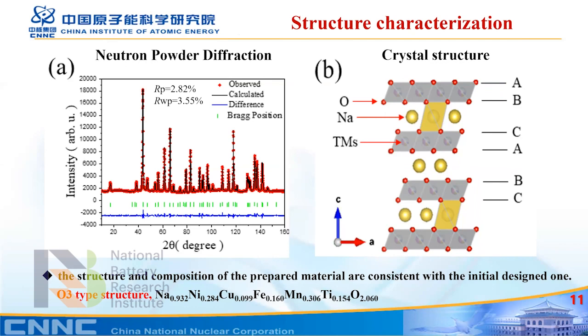That is sodium 0.932, nickel 0.284, copper 0.099, iron 0.160, manganese 0.306, titanium 0.154, oxygen 2.060. The design, I think, is a very good matching. Let's see this. We also carried out the charge and discharge with X-ray.